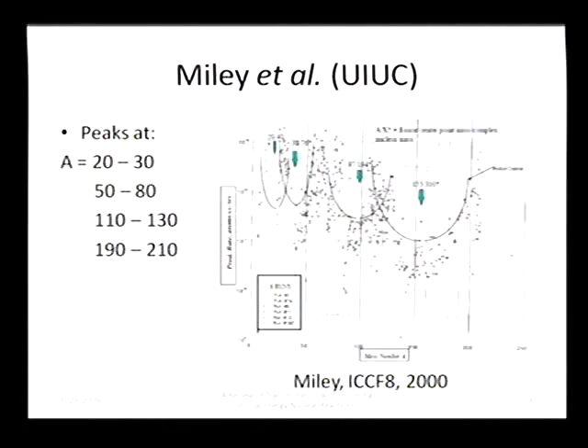The results that he saw were that basically he was seeing peaks of different elements at A of 20 to 30, 50 to 80, 110 to 130, and 190 to 210. Now, none of the particular species he saw were unusual in the sense that they naturally occurred, but what was unusual is that if you look at the natural abundance of the element, these were way out of kilter from the natural abundance.